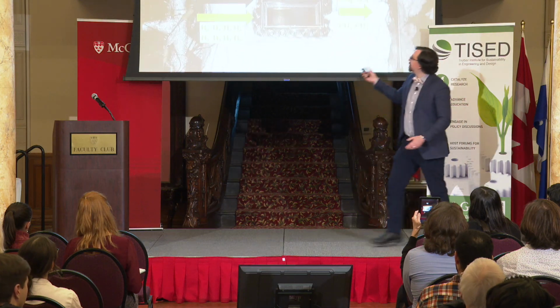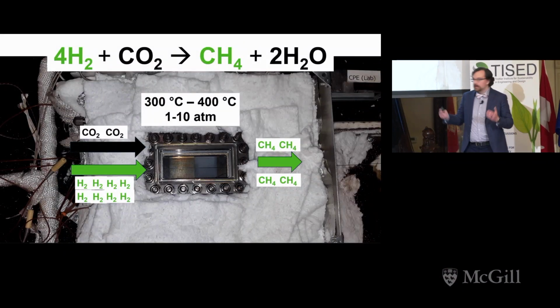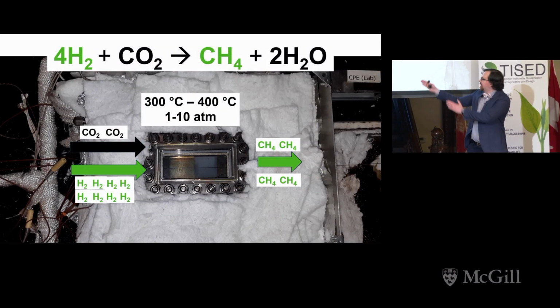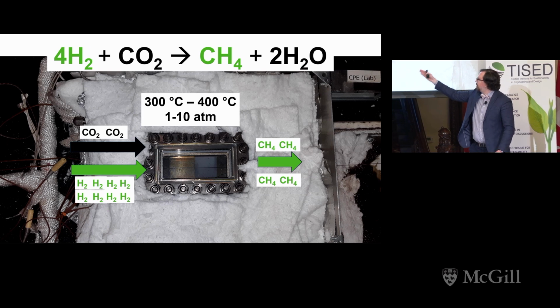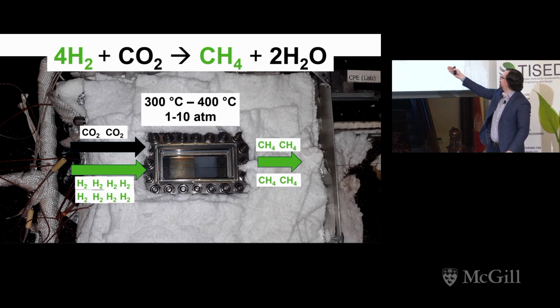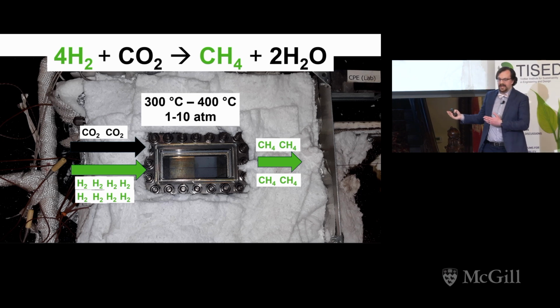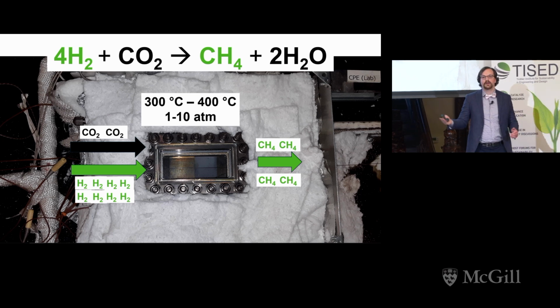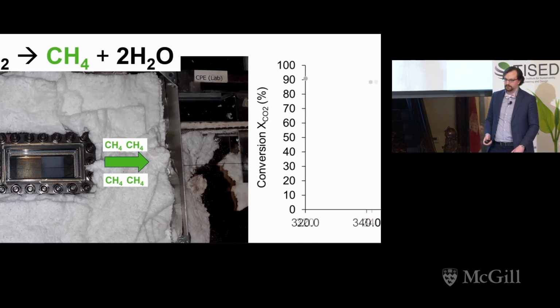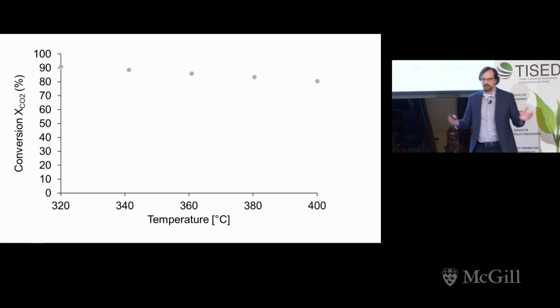This is my reactor. The way it works is CO2 and hydrogen flow across the reactor bed and produce methane. Our reactor usually works between 300 and 400 Celsius, and we can raise the pressure from 1 to 10 atmospheres. Now, how do we measure conversion?